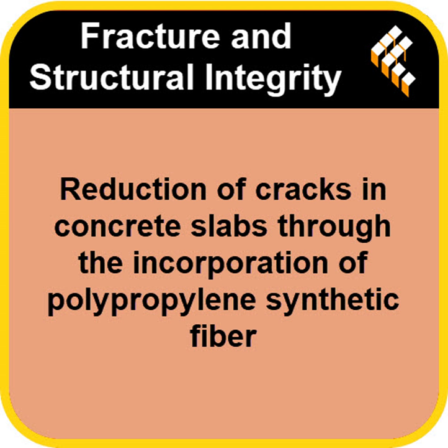And the lighter dose? The lighter dose, DM01, was okay, but an 11% reduction. Good, but not the best. Now, what about the high dose, DM03? Common sense might suggest more fiber means tighter cracks. And common sense would be spectacularly wrong here. DM03 was a catastrophic failure on this metric. It didn't reduce the width. It resulted in a 28.75% increase in crack width. An increase? It actually made the cracks wider. Why?